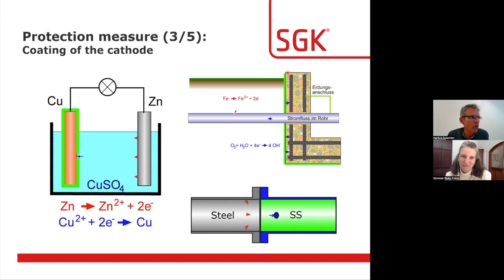We have more and more the case that we have thermal insulation in the foundations, which is not exactly a coating of the cathode, but which introduces a high resistive path here, which also blocks electrical current. That kind of works until the electrical guy insists on building an earth ribbon around the building, and then you're back with the corrosion issue with the copper ribbon around the building.